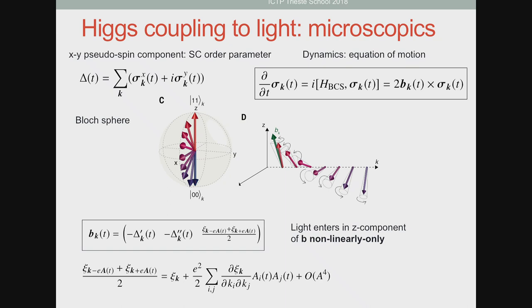Now, what is interesting in this picture is that if you look at this effective field, and in particular the z component, which represents the coupling to light, you can expand it. And if you write down explicitly what this term gives you, you can see that there is actually no coupling to linear order in A, and that the next order comes with A squared. So what this shows you is that when you couple light to this pseudospin, there is no term that couples linearly to the gap dynamics, and the only term that comes is A squared.